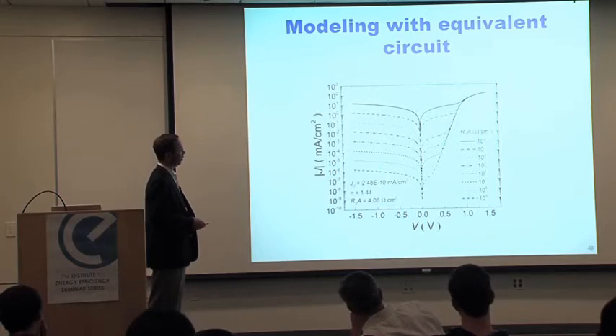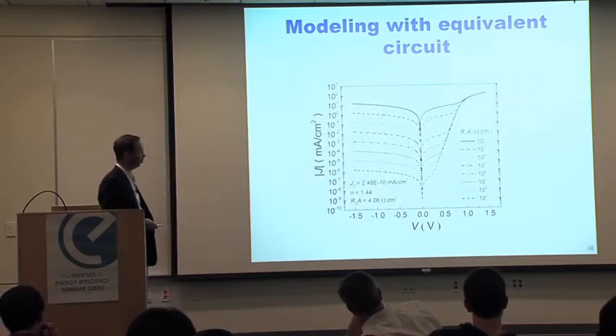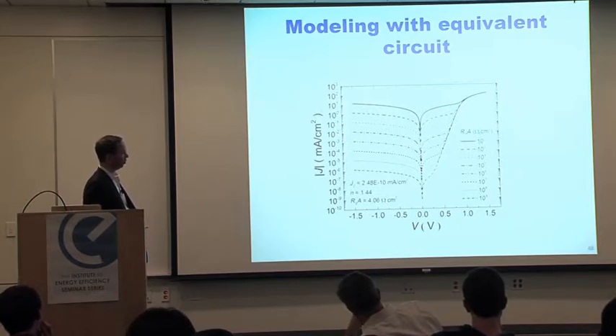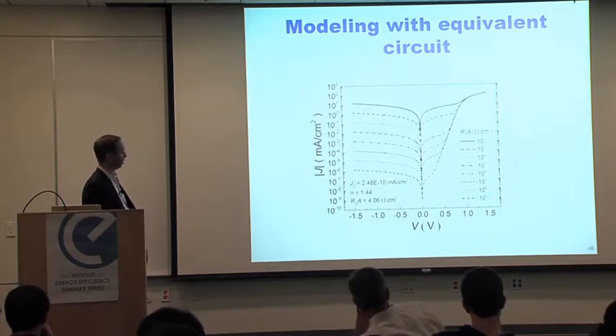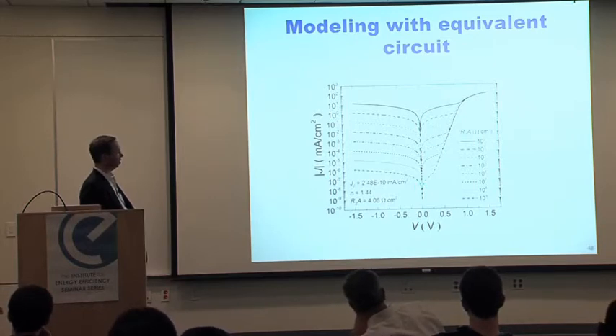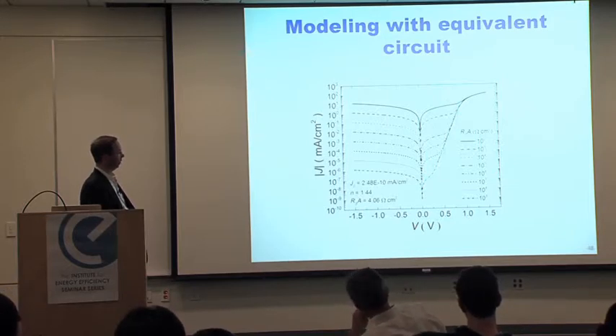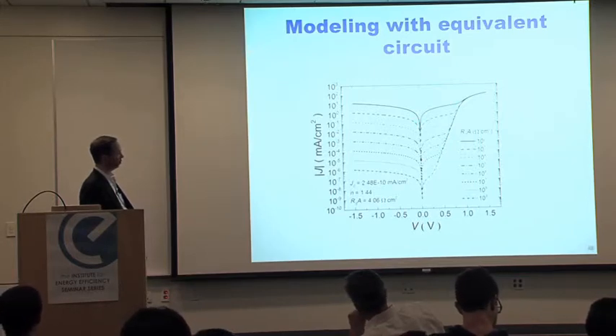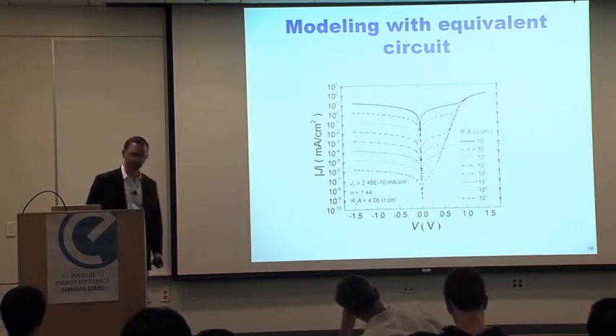These are just calculations based on the equivalent circuit that I showed earlier. The only thing we do is we vary the shunt resistance from about 100 ohms square centimeter all the way up to about 100 mega ohm, or even this is 1,000 mega ohm, giga ohm per square centimeter. And you can see that the shape now of these curves is very typical of what we see in these low and high shunt devices, where when you look at forward bias also, if you have a low shunt resistance, you see that part is just an ohmic behavior due to the current flowing through the shunt resistance before the diode turns on. If you increase the shunt resistance, you see that the diode kicks in much earlier because you have much less leakage.